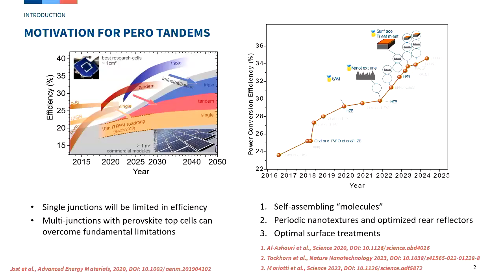The first one here, back in 2020, we introduced so-called self-assembled monolayers or molecules, so-called SAMs. We also heard them yesterday. And what you see is that most of the upcoming record cells from different centers or companies also use those self-assembled monolayers as a contact material today. So this has been something that took over. The second thing that we introduced was periodic nanostructures. At that point, I was very close to the 30%, this psychological barrier that we did not overcome by that time in the certification. But what we also did is we included an optically refined backside of the wafer, and this is also, especially in the KAUST records, included now. So again, something that took over in this community.